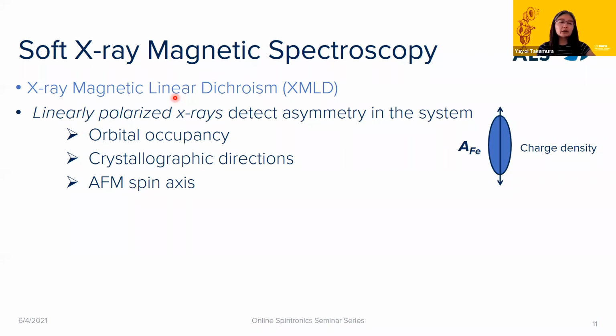One thing you have to keep in mind for this technique is that a priori, you don't really know which asymmetry is leading to the dichroism that you'll see. It could be orbital occupancy, it could be crystallographic directions, or it could be the direction of the antiferromagnetic spin axis. What we hope for is a measurement geometry where, if we have an antiferromagnetic element, so our iron ion in this case is antiferromagnetic, it's going to have some elongation of the charge density around the iron atom. If we come in with linearly polarized X-rays which are vertical, along the long axis of that charge density, or horizontal, along the short axis, we'll get a difference in the absorption spectra so that we can calculate an asymmetry.